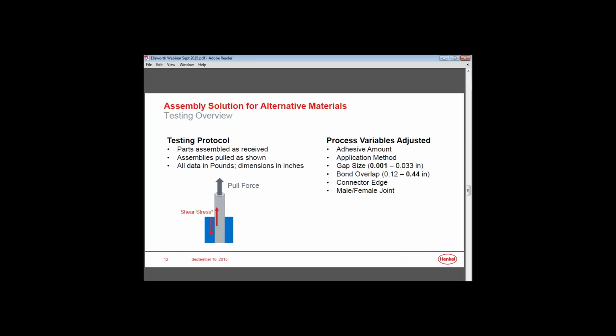So now we're going to discuss how we tested. The testing protocol that we used across the board on the next few slides that you'll see: we assembled the parts as received, and the assemblies were pulled as shown below. That pull force causes a shear stress on the joint, and I have an asterisk listed there because depending on the diameter of the tubing, a more rigid tubing would certainly be in the shear stress mode. As you get to a more flexible tubing and change in the diameter, now you might be introducing the peel mode of stress on your joint, and that's due to the tubing necking and flexing as you're pulling it, which is causing a different stress on the joint. So for the most part, we're saying conservatively it's the shear mode of stress, but as you'll see with the varying diameters of the tubing, you'll see different results as you're introducing that peel.